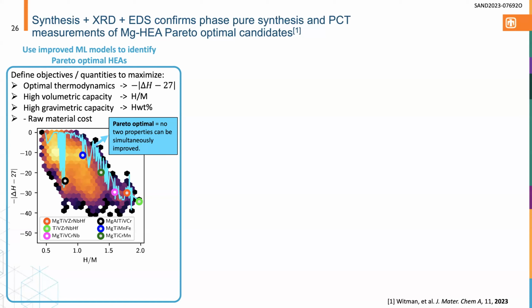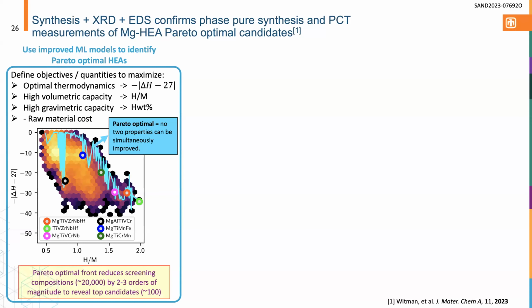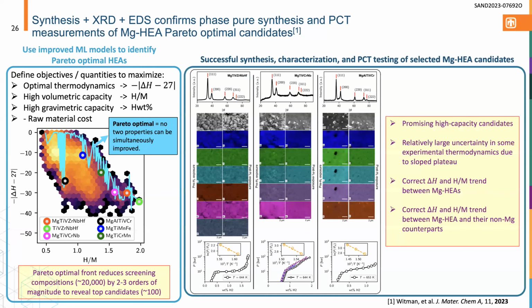So as long as we're operating on this Pareto boundary, we're essentially guaranteed to be predicting an optimal material for a particular use case, and that's why we've focused on that in this subsequent study. So you can see some of the materials we've tried to make. It reduces the screening space of possible high entropy compositions from equimolar compositions from 20,000 by many orders of magnitude to just 100. So there's only really 100 on that Pareto front. So again, a manageable number to actually select for experiments. And then we passed them over to the experimentalists.